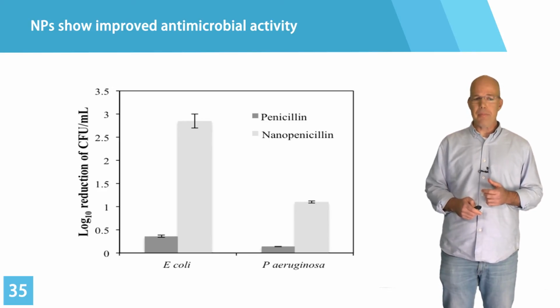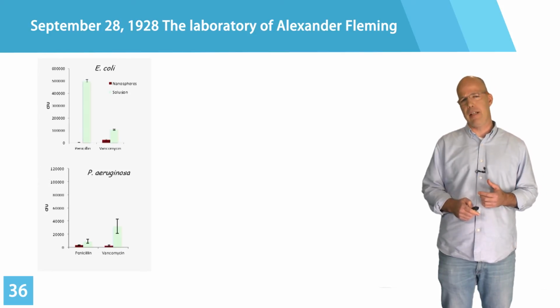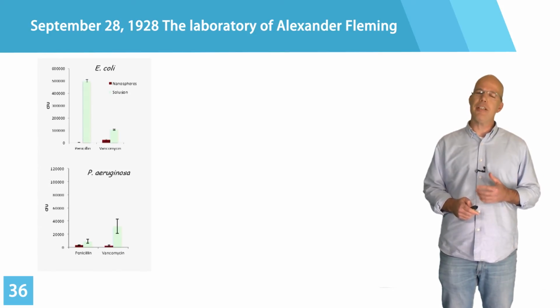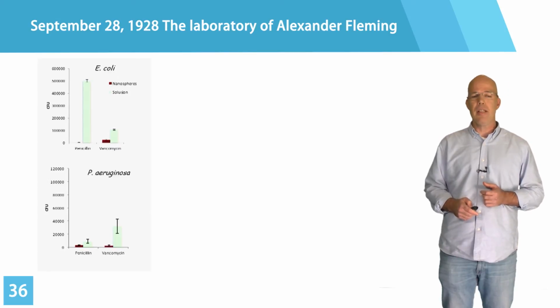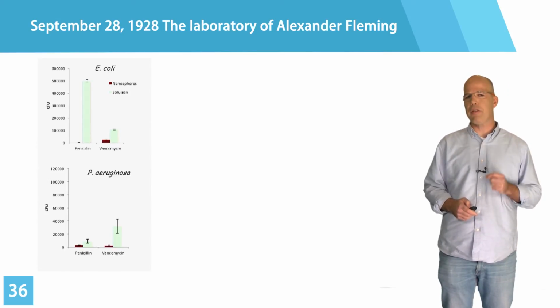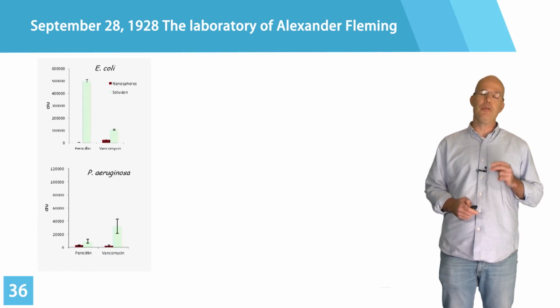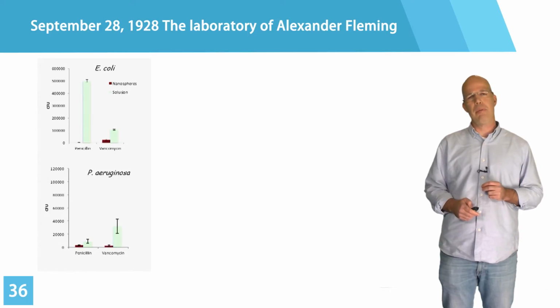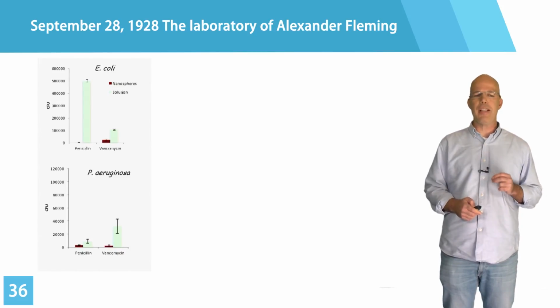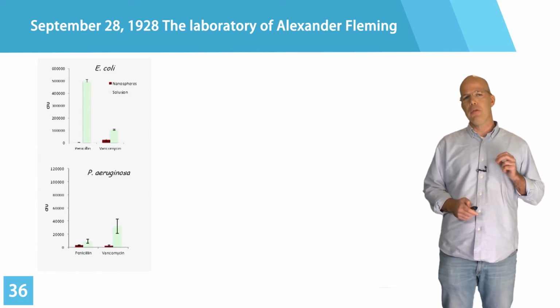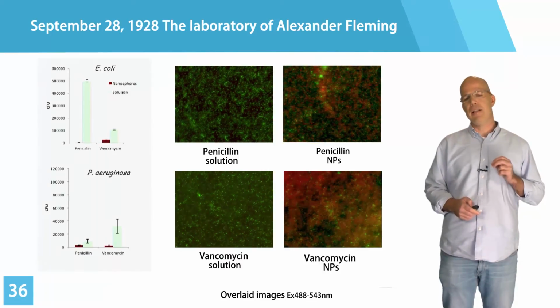In fact, Professor Tzanov went another step ahead and actually tested the activity against biofilms. And here, I remind you that biofilms are extremely resistant to antimicrobial therapy. And he used 2 strains to study it, 2 bacterial pathogens that often form biofilms, E. coli and Pseudomonas aeruginosa. And you can see very nicely that again, if he uses the nanosphere, the activity is much higher. And in red, what you see in the images are dead bacteria.